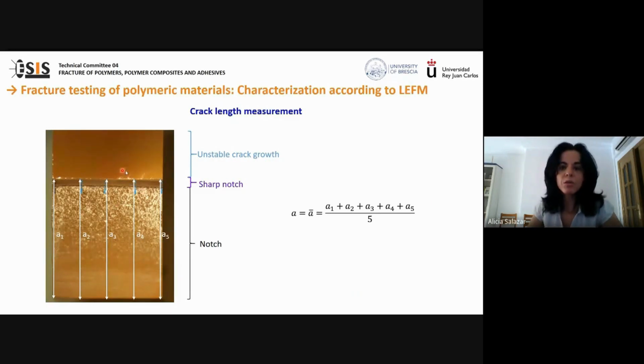This photo shows the fracture surface of an epoxy resin where the machine notch, the sharp notch, and the stable crack growth are visible. The total crack length after notching and sharpening is obtained as the average of 5 values, 2 measured on the surface, 1 at the center of the specimen, and 2 values measured midway between the surface and the center of the specimen.